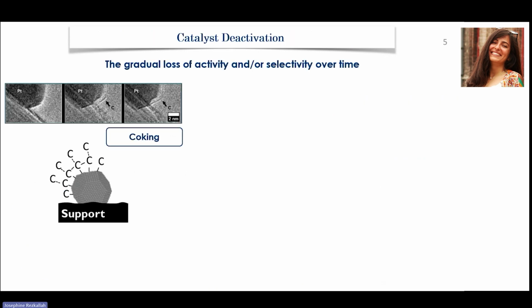The answer is no. During the chemical reaction, the activity of a catalyst is reduced over the course of the reaction. It's a loss in activity attributed to several transformations a catalyst undergoes that can lead to its deactivation. One of these transformations is known as coking. This is the effect of the chemisorption of carbon on the catalyst surface. The carbon, for example, deposits on the platinum nanoparticles, as you observe in this example, leading to blocked active sites and eventually loss of platinum activity.